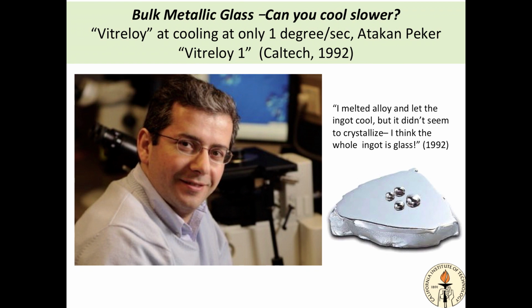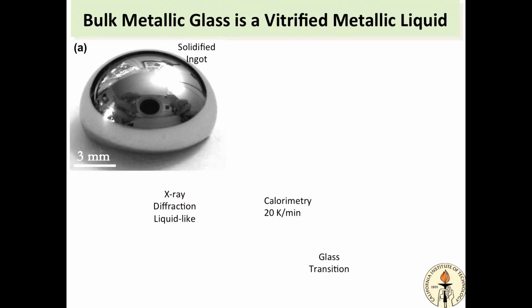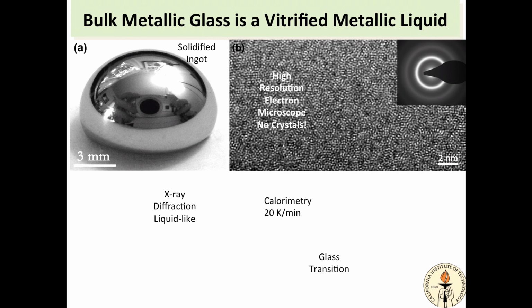and this was a very good glass former, kind of like silicate glass. It starts to look like more common glass. That's a nice ingot. We put it in the electron microscope and blow it up about 400,000 times, and you can see atoms, or you can resolve atoms, and they're all jumbled up. It's liquid-like, no crystals. If you look around, you'll see pentagons that are part of icosahedra and all that. It's a nice glass. And so